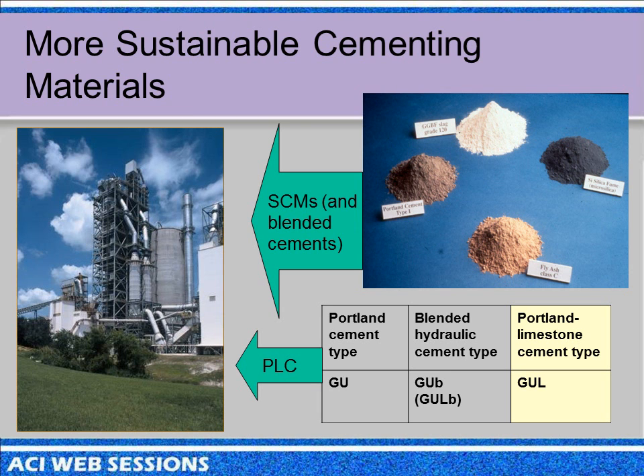And this is not to replace supplementary cementing materials. People are either making blended cements or using pozzolans and slag at the ready-mix plant to get special properties: sulfate resistance, low heat, alkali aggregate resistance, increased corrosion resistance. They do that anyway, but we don't want to impact that. So the idea of Portland-Limestone Cements is they complement this, they don't replace that.